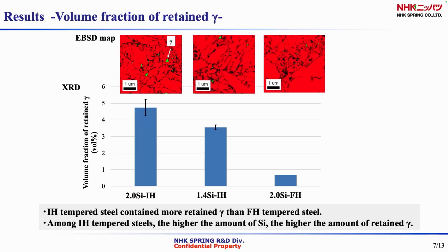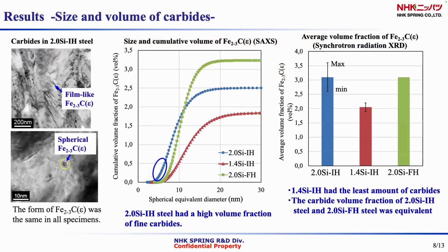It was found that IH tempered steel contained more retained austenite than FH tempered steel. Among IH tempered steels, the one with the highest amount of silicon had the highest amount of retained austenite, which is consistent with previous research. This is the result of the size and volume of the carbides.